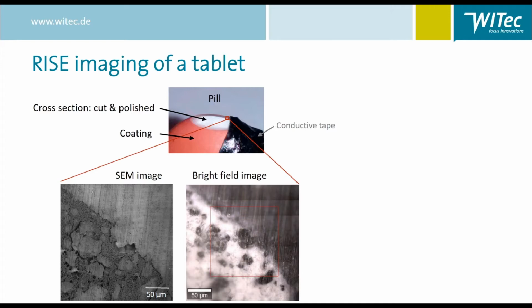Also, a coated tablet has been analyzed by RISE. For this purpose, the pill was cut and polished and then mounted in the SEM chamber with a piece of conductive carbon tape in order to avoid charging. The SEM image on the bottom left reveals areas of different morphology. The area top right is supposed to be coating. The bright field image on the bottom right looks completely different, indicating that it would be troublesome to find the same sample area, again, if the system was not fully integrated.